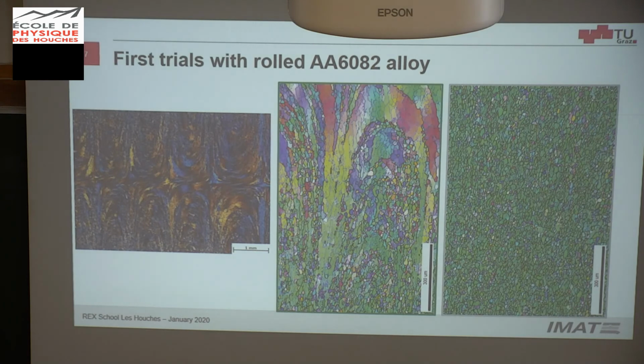So the first trials, please, on aluminium alloys showed something like this. This is light optical microscopy along the gauge, and this is EBSD. What you see is that the microstructure is very heterogeneous. So we didn't cut as usual. People cut at a given percentage here, and then only watch the microstructure to represent the global strain and stress values. What we wanted to do was to see the evolution of these boundaries. Here in blue you see low angle grain boundaries, and in black high angle grain boundaries.